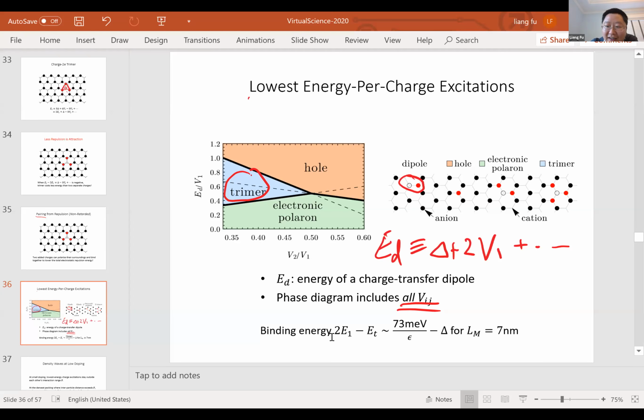In terms of numbers, the electrostatic energy is a large quantity, but the binding energy, the energy difference between a trimer and 2 holes, is actually a small quantity. Based on our estimates, it's about 73 millielectron volt divided by the dielectric constant minus the charge transfer gap. So this quantity is probably on the order of 10 millielectron volt or even less.